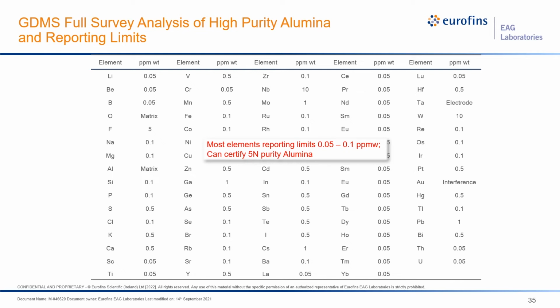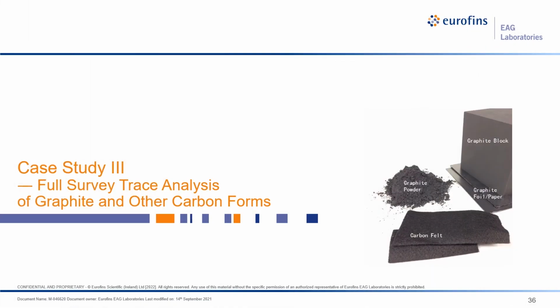Here shows you the GDMS full survey analysis capability for high purity alumina. It covers all the elements from lithium all the way to uranium. And for most elements, the reporting limit is 0.05 ppm to 0.1 ppm. So they can easily certify 5N purity alumina. The third case study relates to graphite and carbon forms.